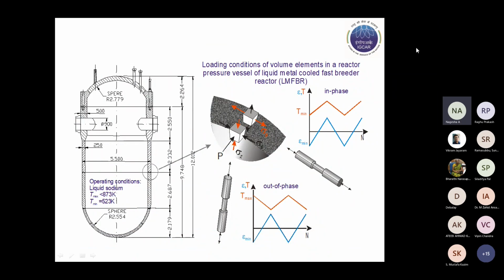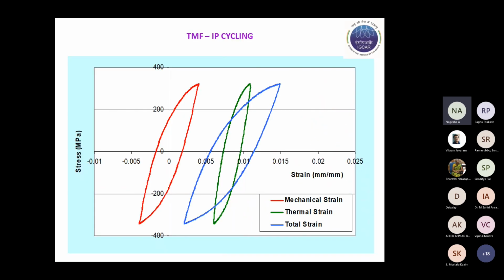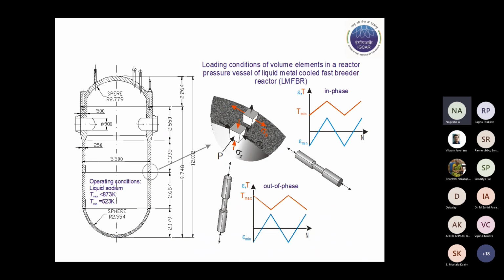Okay. So this shows different kinds of strain-temperature sequences that happen on the inside surface and the outside surface. Whereas inside and outer surface we have an in-phase relation, it can get balanced by the out-of-phase cycling on the inner surface. Since these are two extreme cases, they will generally give rise to the extreme variation in the temperature. Hence, these two generally are used. Of course, there can be any number of combinations between the strain and temperature, but in general, these are the two things that are investigated.